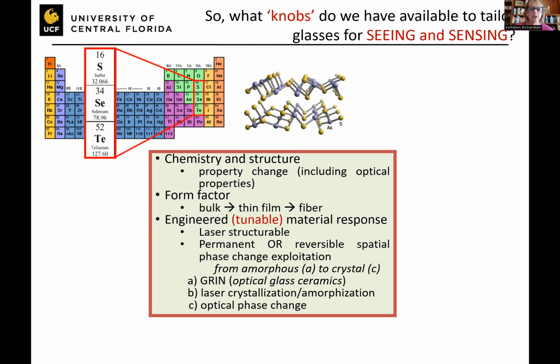We can certainly change the chemistry and thereby the structure of the glass, and this will allow us to change not only the optical properties, but many of the other properties. The bonding in chalcogenides is typically mixed between covalent and van der Waals forces, which in this arsenic sulfide layer structure, covalent bonds exist within these layers, but it's van der Waals forces that bond these weak bonds in between layers.